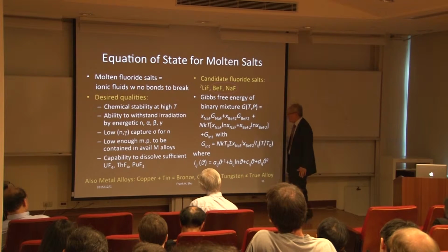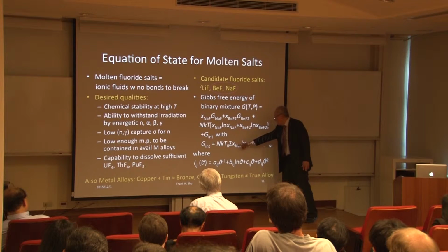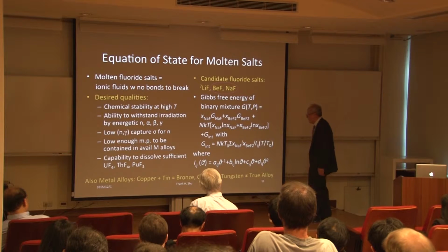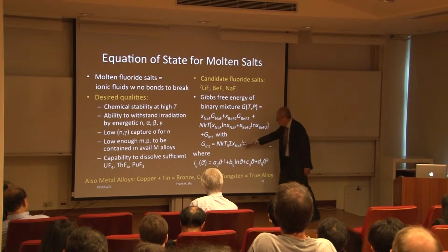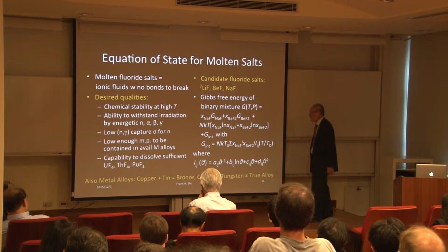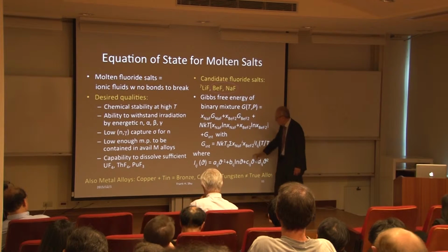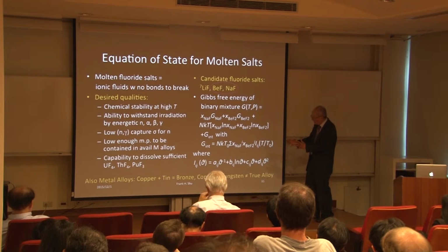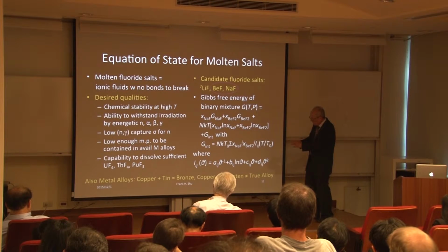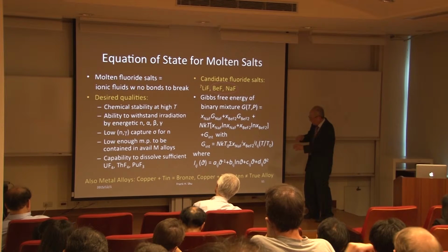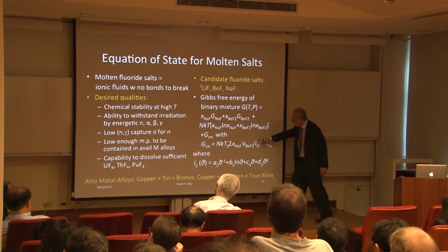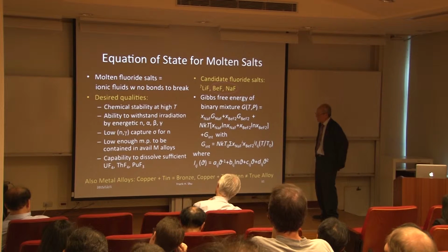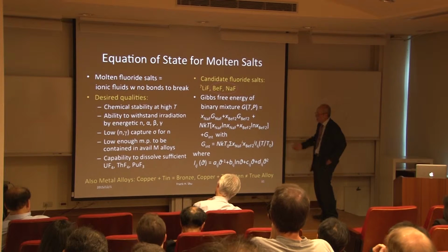So to get the right dimensions, nkT times two products of x's times some function of the temperature. The T0 is just some arbitrary temperature, let's say 1,000 Kelvin, okay? What does this represent, though? It really means that in a liquid, or in a solid for that matter, things are so close, you not only have binary interaction, they can interact with 3 at a time, 4 at a time. So you have to consider all those possibilities, i and j. And you can include enough of them so that you can explain the observation. So it's just purely an empirical thing.